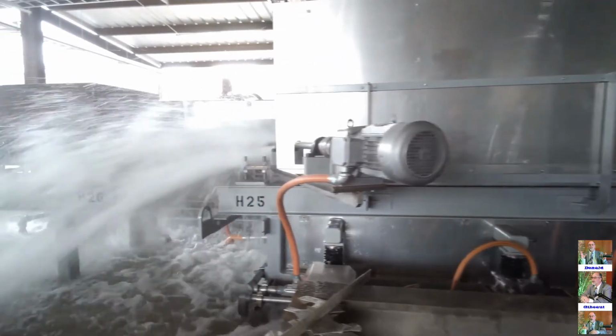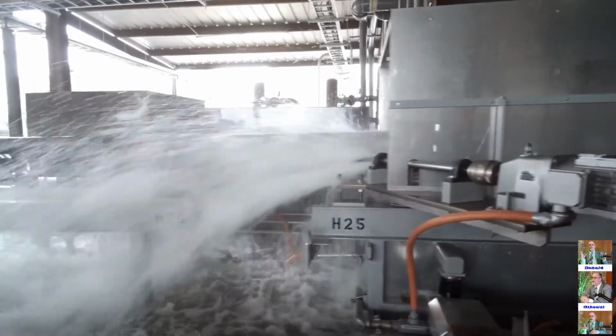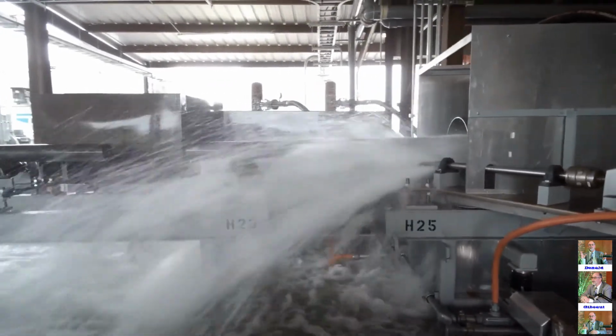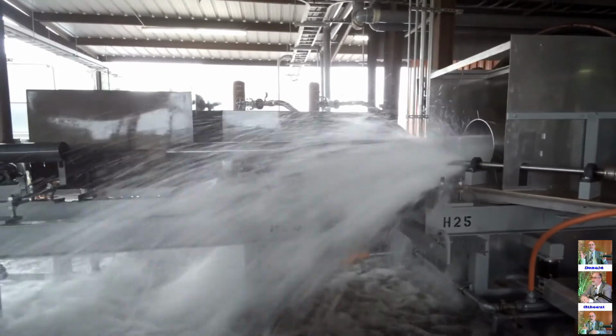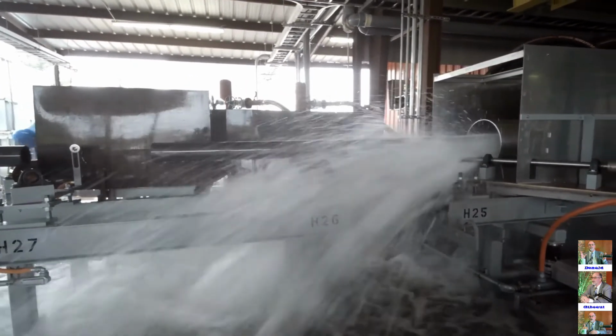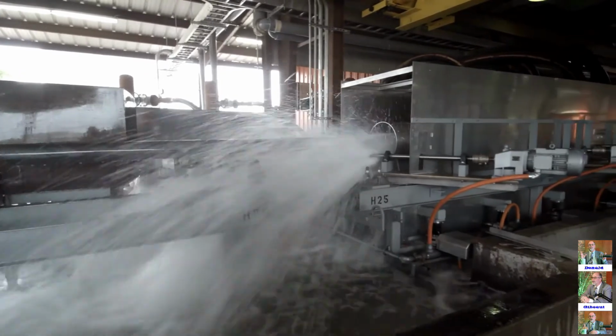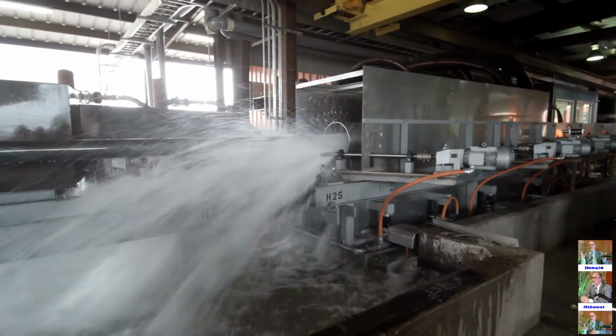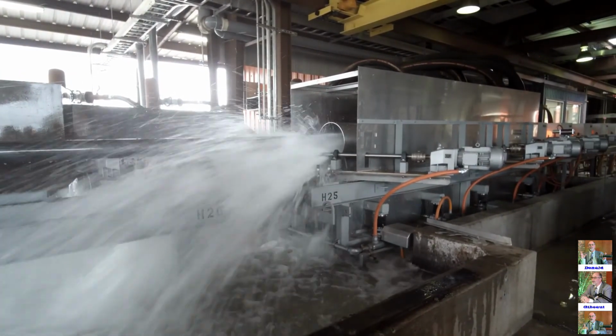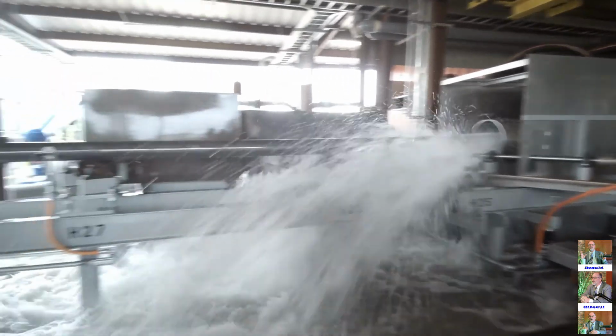Now you can see the volume of water coming out the tail end of that quench system. Got quite a volume. You got a river flowing here. But again, when you look at the TTT curve, it's a very aggressive process. You need this flow and this aggression. And you can see the adjustment, the jack screws underneath the whole quench assembly to keep the quench centered.